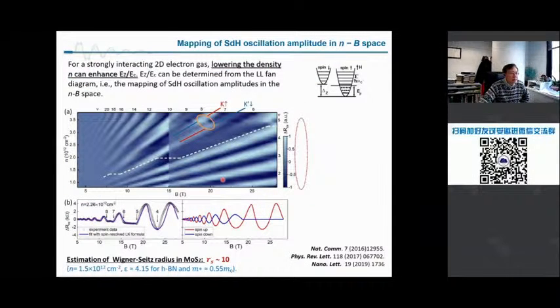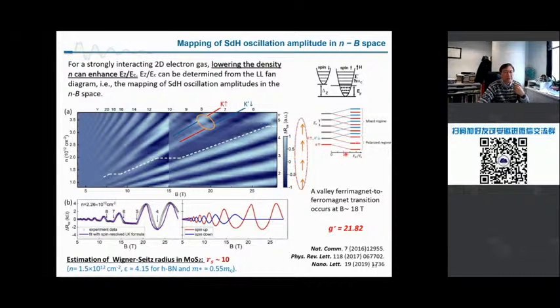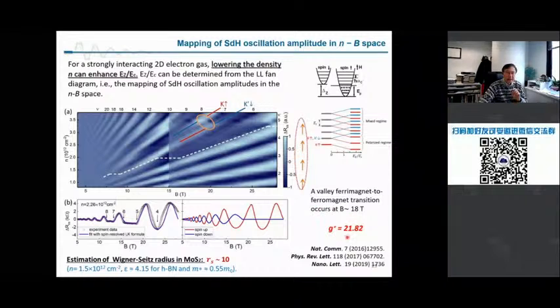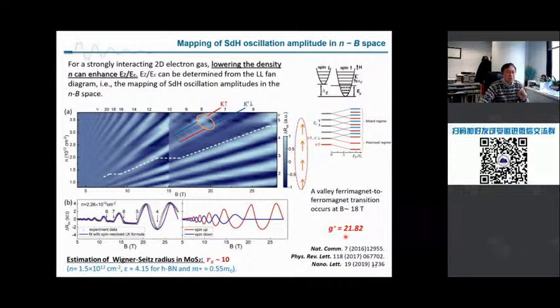All right, so I'll show you this map to give you the experimental results, so that you understand the principle: for high filling factors, you have spin up, spin down, spin up, spin down, until 6, 4, 5, 2, 3, 2, and 1 is isospin. This is isospin. It's like this polarized region. That's called the ferromagnetic transition at high magnetic field. And then we further determined the splitting of this energy gap and determined the G factor is really high. So in the future, if you want to study materials and explore electron interaction behaviors, this is a good candidate material.